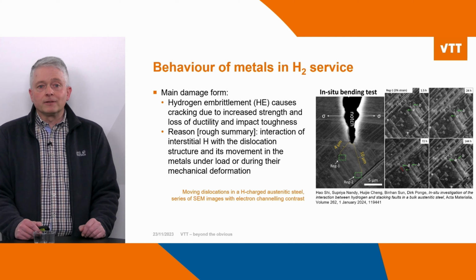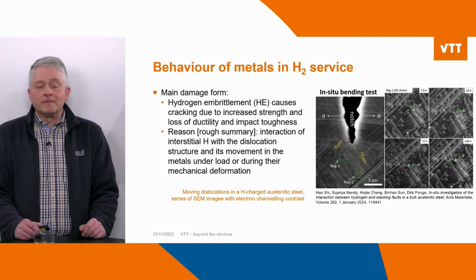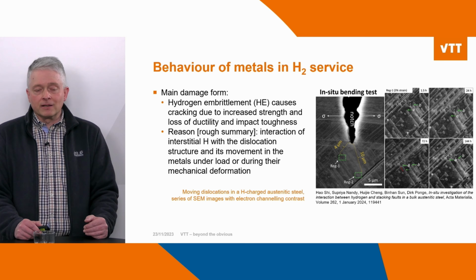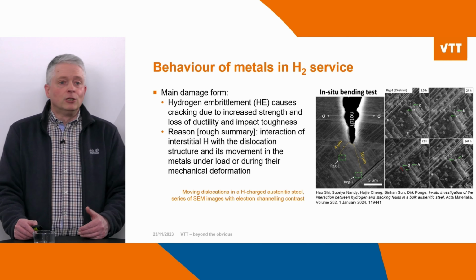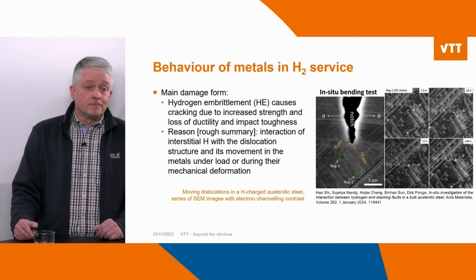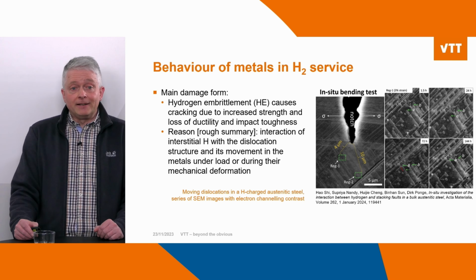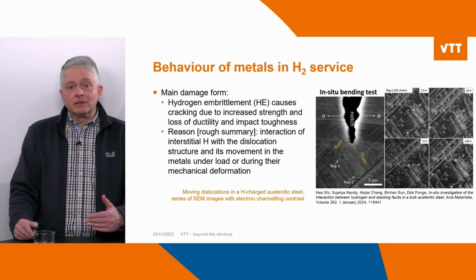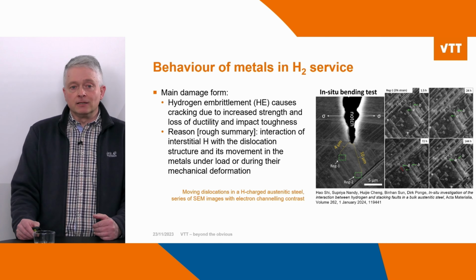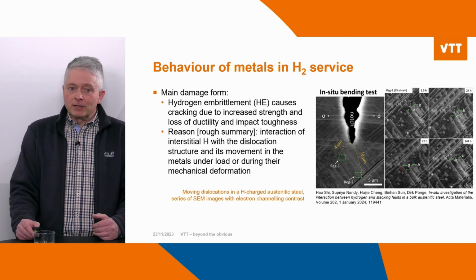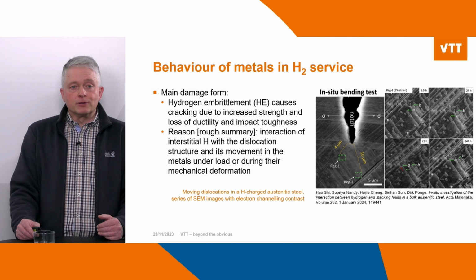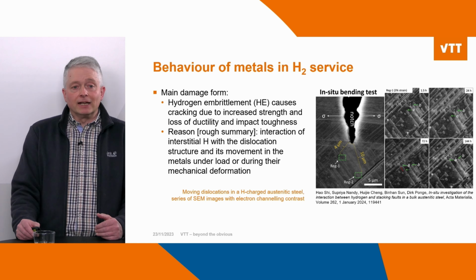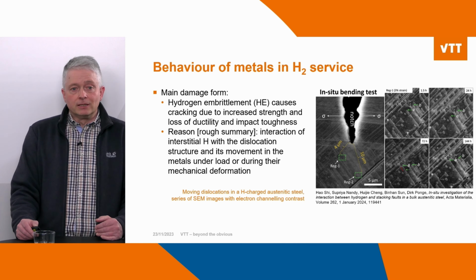In the picture after 72 hours, some dislocations have moved. This material was also under mechanical load, and this was caused by hydrogen. When the authors of this study did a similar experiment without mechanical stress, they did not observe this. So this is a clear effect that hydrogen interacts with dislocations in metals.